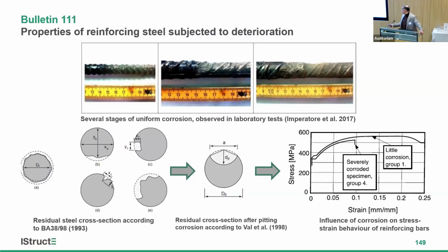And this is another model by Val et al. That is essentially considering how we can account for the pitting corrosion. So if we can measure the corrosion on site, if the rebars are essentially exposed, we can use one of these models. The equations are available in the bulletin to account for the residual diameter, residual cross-section area of the corroded bars. But that's not the only effect that corrosion has.